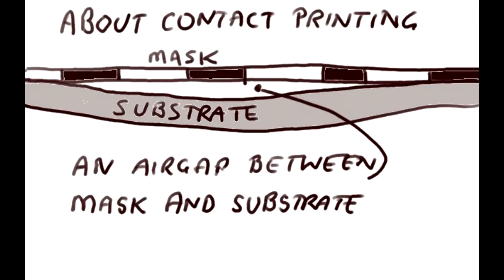However, I'm talking about contact printing here. When you contact print a flat substrate onto a flat mask, you'll get an air gap with an MA6, for instance, aligner. So the air gap, however it's caused—it can be caused by upstanding features on your substrate or anything like that—the air gap is really going to change the profile of the resist you get according to your exposure.